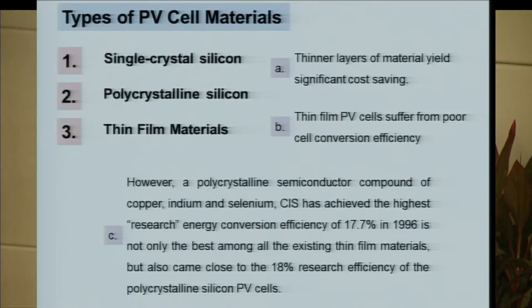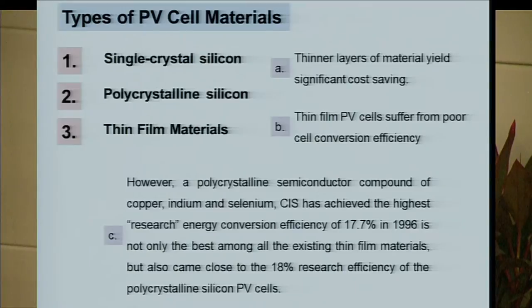However, as it is now, the gap in conversion efficiency between thin film and silicon is very wide. The thin film has a much lower conversion efficiency. But in 1996, they developed a semiconductor compound consisting of copper, indium, and selenium, or CIS. This compound achieved an energy conversion efficiency of 17.7% in 1996, so it rivals that of silicon solar panels. That's another reason why we have dwelt on this particular material.